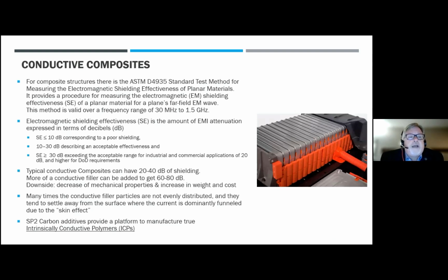As a conductive composite, there is an ASTM test method for measuring the electromagnetic shielding effectiveness within a planar material. This is one of the test methods and standards that are out there, and it provides a procedure for measuring the electromagnetic shielding effectiveness of a planar material. We can touch on this a little later in our presentations as well. This method is valid for frequencies of 30 megahertz to 1.5 gigahertz. Electromagnetic shielding effectiveness is the amount of EMI attenuation expressed in terms of decibels.